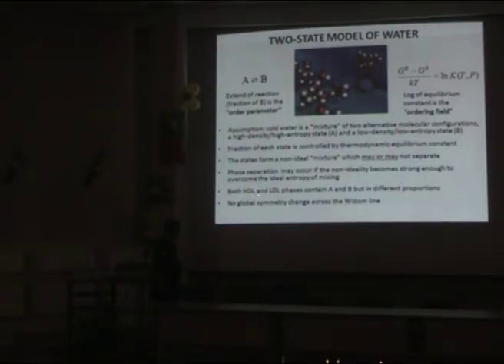Both high-density liquid and low-density liquid contain A and B, but in different proportions. The lower the temperature, the more and more water contains the low density, low entropy fraction. And most importantly, there is no global symmetry change across the Widom line. Widom line is the continuation of the phase transition line into the homogeneous region, like the critical isochore in liquid-vapor transition. And there is no symmetry change. We can go from one liquid to another liquid without a phase transition. Next slide.